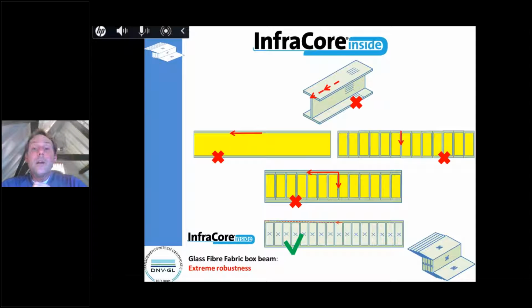And in the middle, you have a blend between the two approaches, which is again a pultruded box assembled structure, but then surrounded by facing structures. And these red arrows again are showing potential crack growth paths. And if it goes, it goes. And on the bottom, that's our approach.